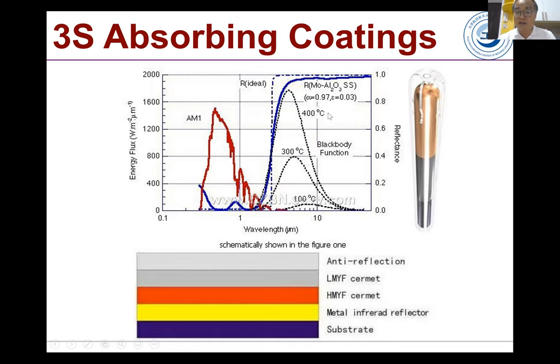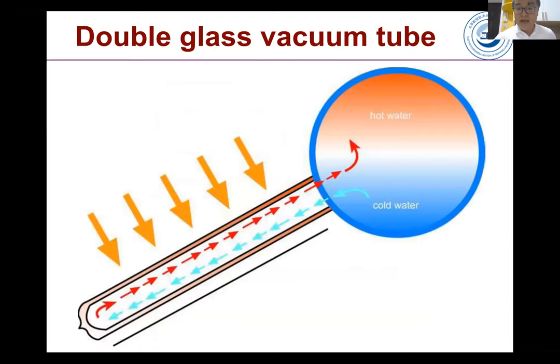And so this is actually a very good solar spectrally selective coating. Here the reflectance is very high, meaning the emittance is very low. You see the emittance is 0.03, which means the thermal loss has been controlled as low as possible. So this is something like the 3S solar coatings. And these coatings have been used in water heaters,